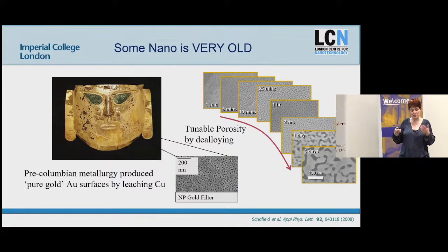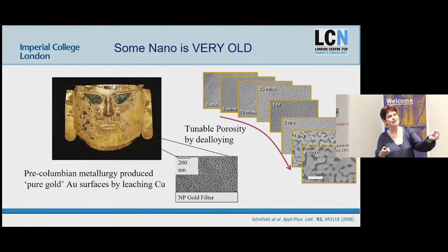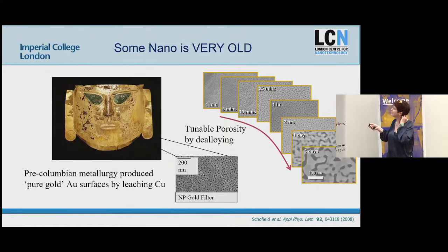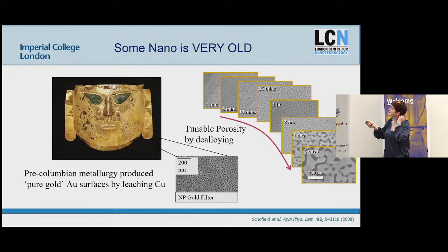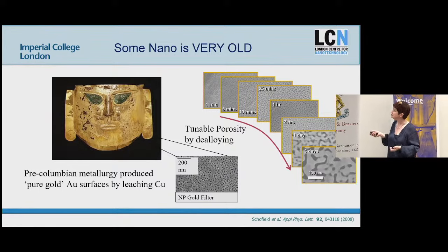This de-alloying phenomena, it turns out, when you dissolve the copper out of copper gold, or the silver out of silver gold, you create nanoporous structures like this. And this is some beautiful data from one of my students, Eleanor. And you can see this self-similar fractal dimension that you get. And this is driven by surface diffusion, thermodynamics again, controlling what the pore size looks like.